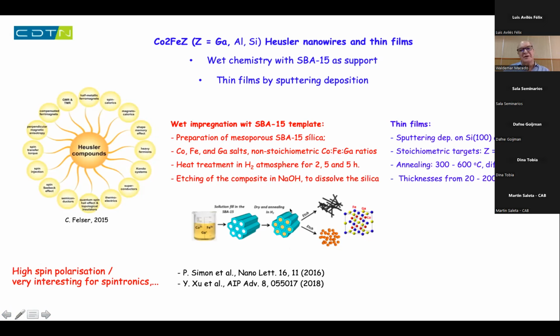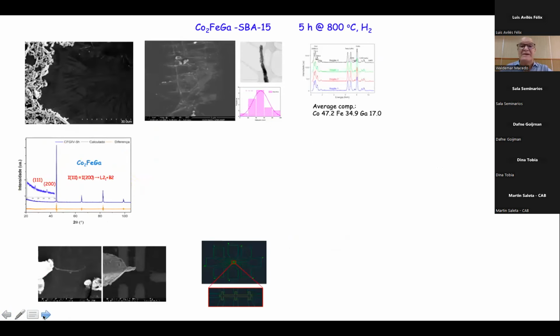You can induce the growth of wires in the walls of this mesoporous silica, and also in internal channels. And we did a lot of work during the pandemic with that. We started growing this kind of material. We see that we got nanowires induced by the mesoporous silica, and then we remove the silica and get the metallic wires. We see some deviation in the stoichiometry. We didn't do much analysis of the materials because of the pandemic, but if you do X-ray diffraction, it seems that you really have the good order, the L2-1 or B2 phase of the cobalt iron gallium